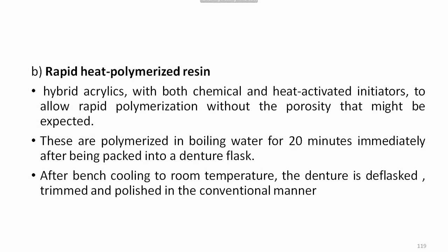Another modification of heat cure acrylic resin is rapid heat polymerized resin. How is it different from your heat cure acrylic resin? Hybrid acrylics with both chemical and heat activated initiators to allow rapid polymerization without the porosity that might be expected. These are polymerized in boiling water for 20 minutes immediately after being packed into a denture flask. After bench cooling to room temperature, the denture is deflasked, trimmed, and polished in the conventional manner.